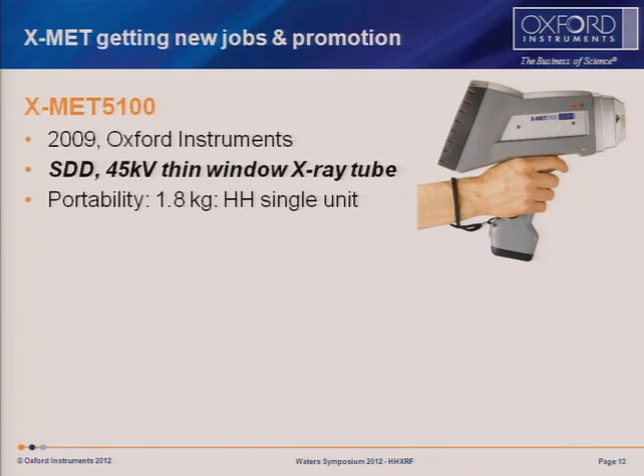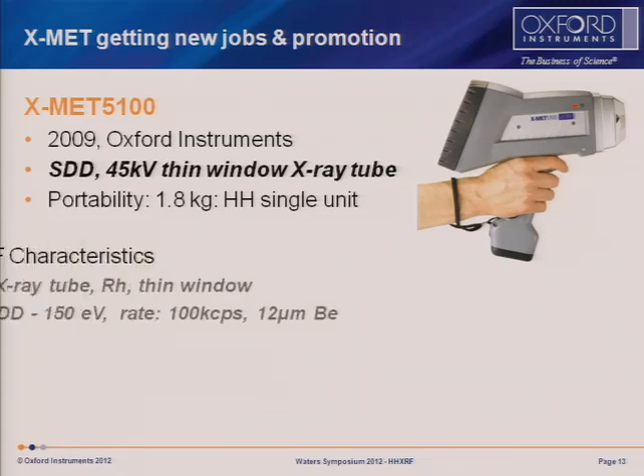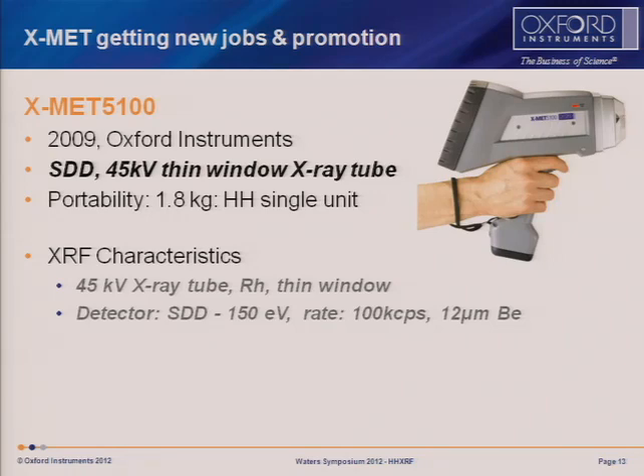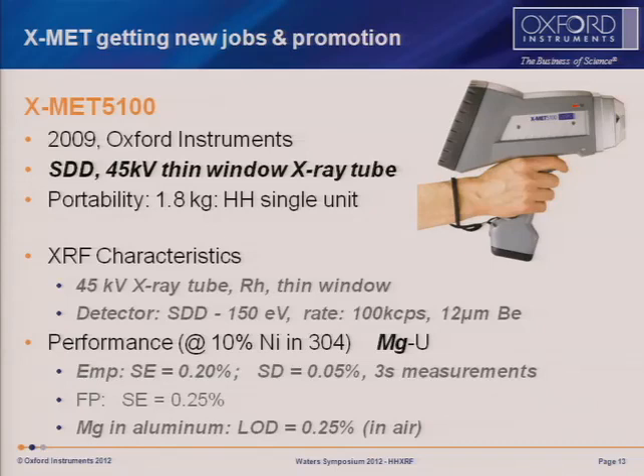It morphed along. 2009, as we heard a moment ago, the introduction of the silicon drift detector really transforms in two ways. It transforms it on the basis of a much better energy resolution, much sharper peaks, better spectroscopy, but also the count rate. Something we were always told in energy dispersive XRF you can't have is sharper peaks and greater intensities. The drift detector's done both simultaneously, and that truly is a step in the right direction. In addition, the improvements that we're now seeing in X-ray tubes, higher kV, and better sensitivity for light elements, in particular now bringing our standard deviations down to 0.05.